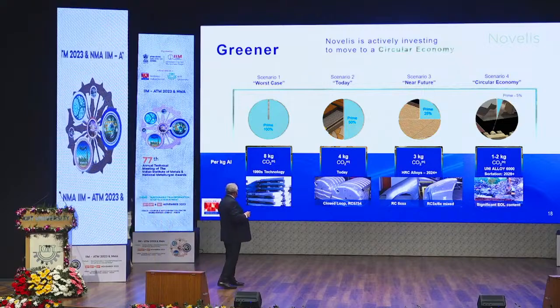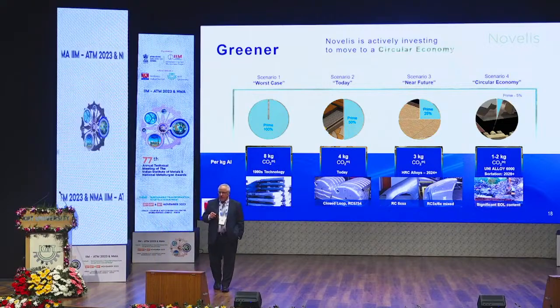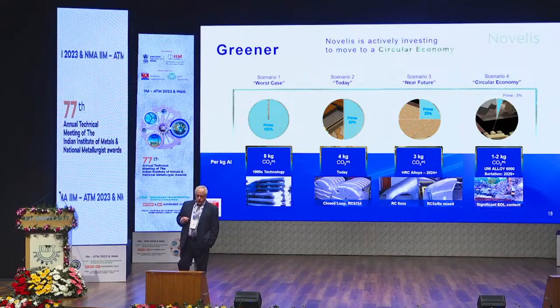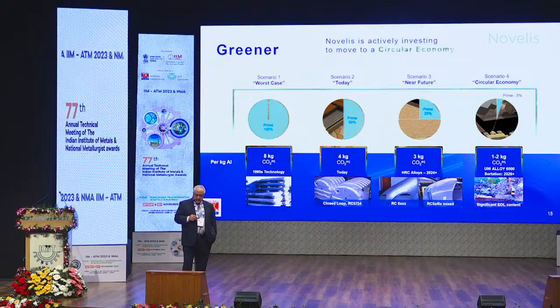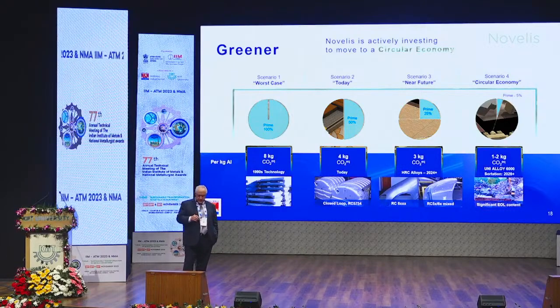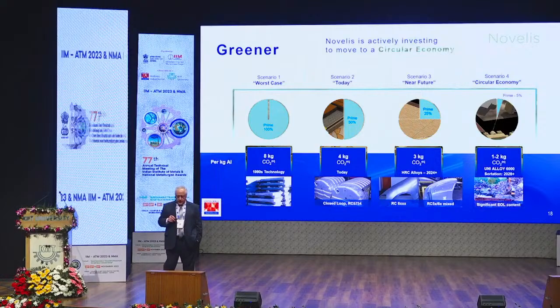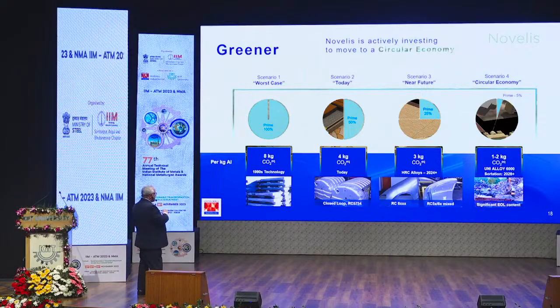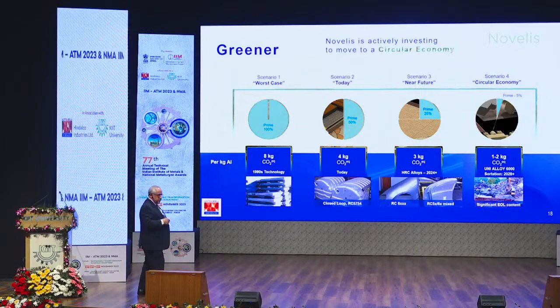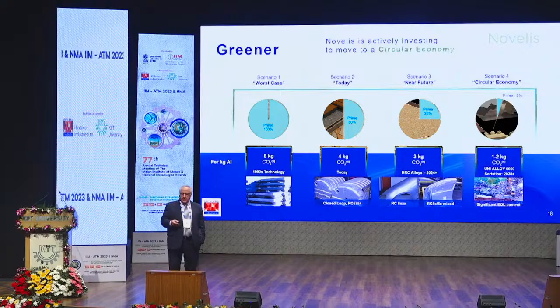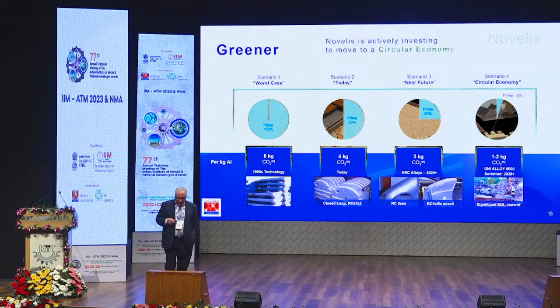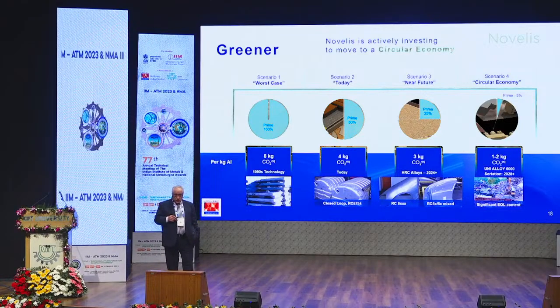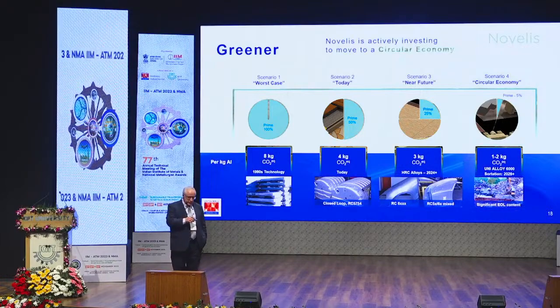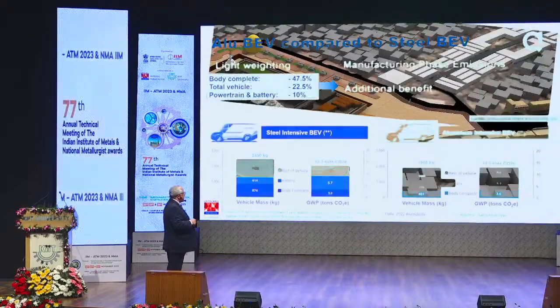In terms of CO2 footprint, what's the impact of the recycling content I told you before? Basically, we're today 50-50, about 50% of recycled material and 50% of prime. And here you see the evolution of the CO2 footprint if we progressively move to full recycling content and full circularity. So going to 1 to 2 kilo of CO2 per kilo, which is roughly 4 times less than what we do today.